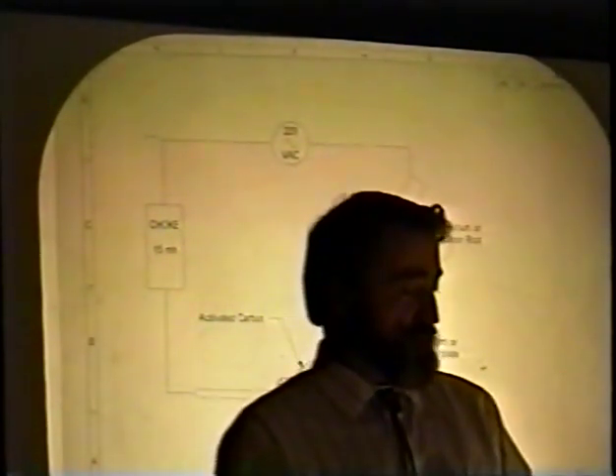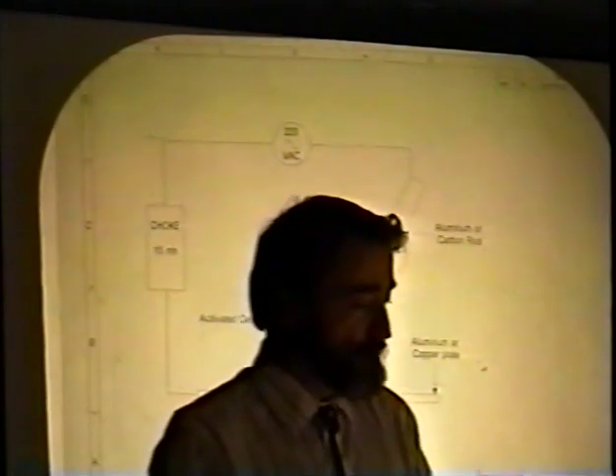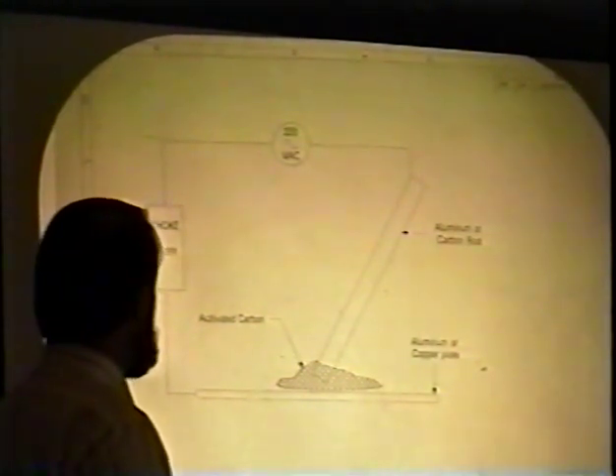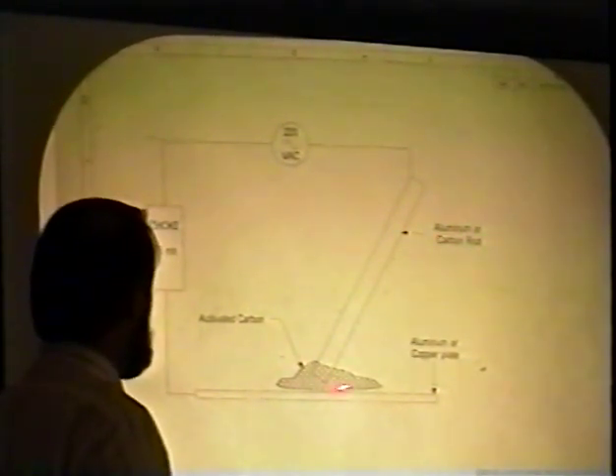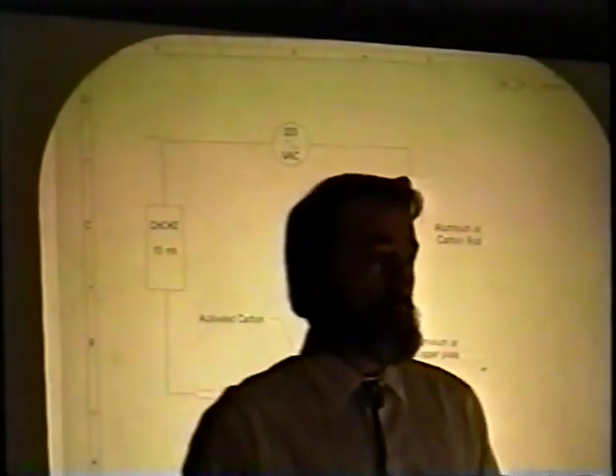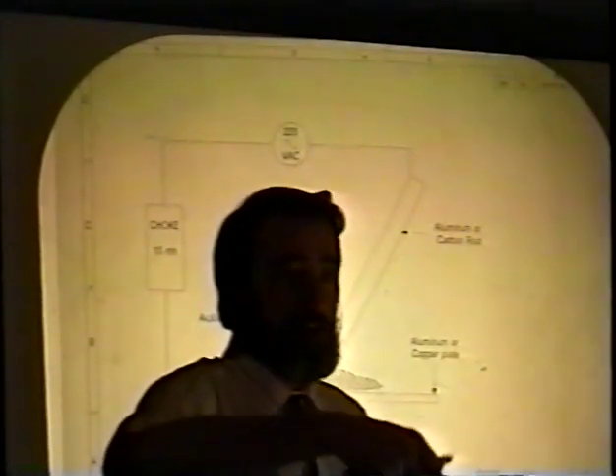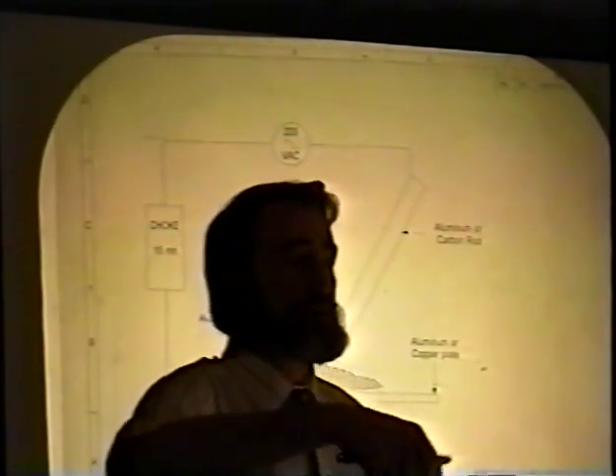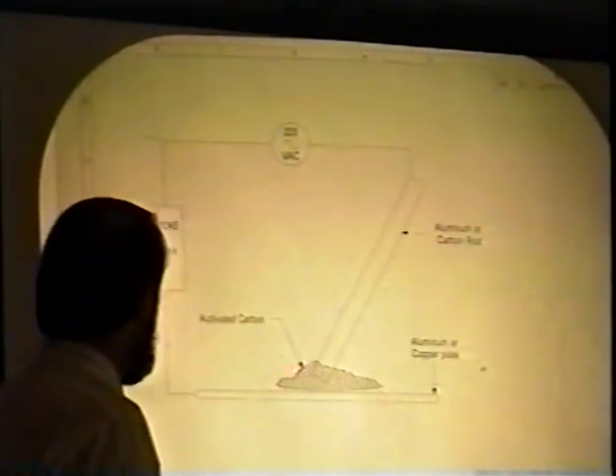So we started out with a similar setup in which we used a 50 amp source from a house circuit breaker, a home circuit breaker. We limited that current by using a 15 millihenry choke. We used a carbon rod, or as I'll tell you in a minute, an aluminum rod, to stir the activated carbon for periods of up to 40 minutes. So basically you sit there in a very uncalibrated stir mode. You stir the carbon with the rod and you see a lot of sparks and basically a short circuit occurring. There's an arc discharge occurring between the carbon rod and the activated carbon or carbon source that you're using.